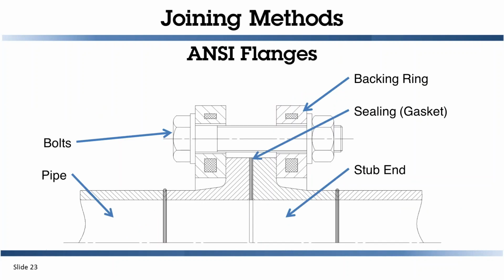If you have larger sizes or are transitioning to metal systems, a flange is the easiest way to do that. Flanges with plastic systems often have what we call a stub end, which you see on the bottom middle, and you have two sides of that with a sealing in between, typically a gasket. Then you have backing rings that have a metal core on the inside that gives it rigidity and strength. Those are bolted together and create a sealing point at the flange.